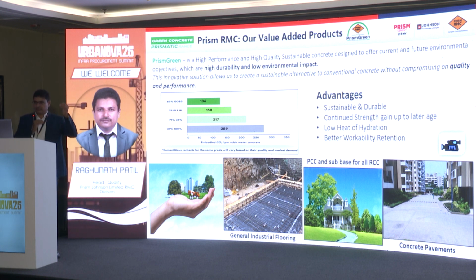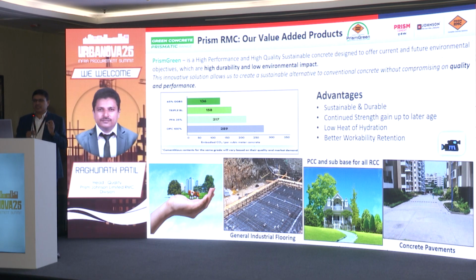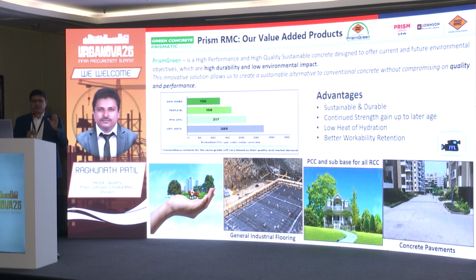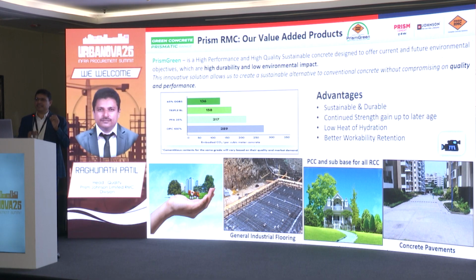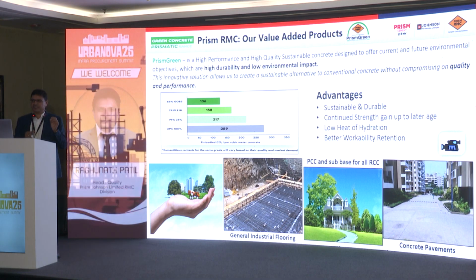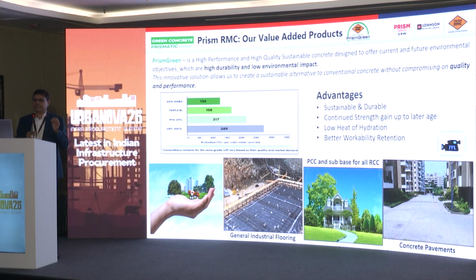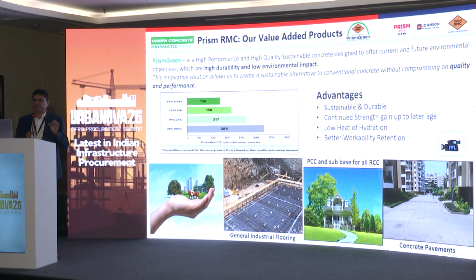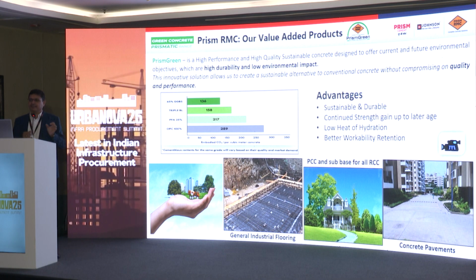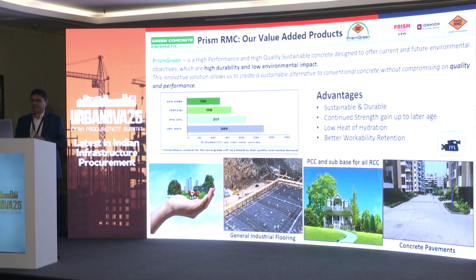We use only that percentage because this aggregate has more porosity. The mortar generally adheres to the aggregates, water absorption is high, and specific gravity is low. That's why the limitation is given in the codes, so we replace up to 20% up to M25 grades.